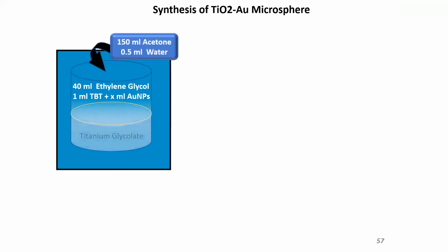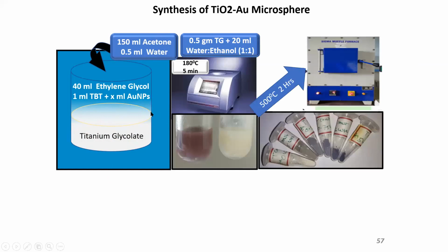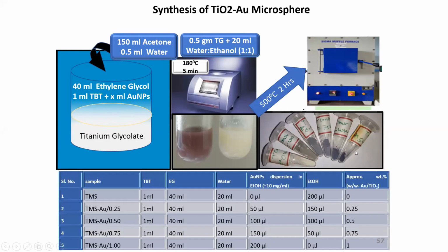So based on that, I drafted one synthesis protocol which uses no acid, because gold and silver can react with acid. It just takes ethylene glycol and water. And the gold nanoparticles I synthesized, I just mix with this solution, and this is the result. So this is just a TiO2 nanoparticle. Now I am not fabricating TiO2 separately and putting gold in separately. I made a one pot synthesis of gold as well as TiO2. And as I add gold inside my material, we can see the color getting darker, with increasing gold weight percentage in the material.